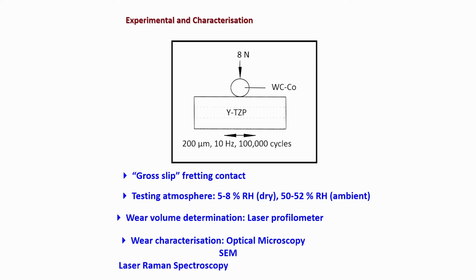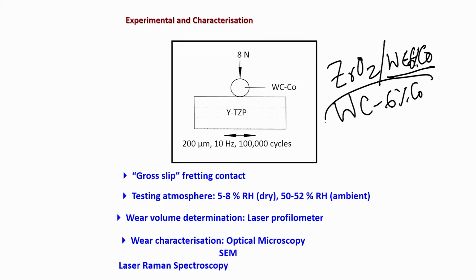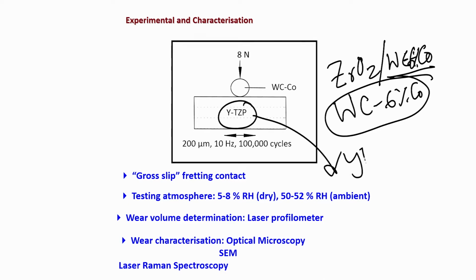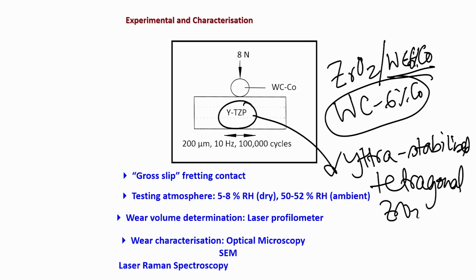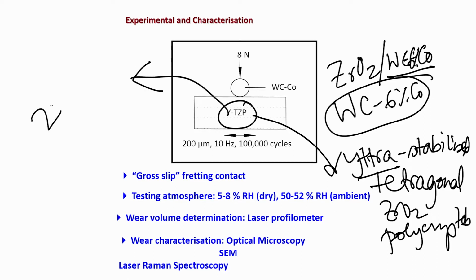So, we have not only used zirconia against transformation toughened zirconia in one of our studies. That is called self mating, zirconia versus zirconia. But in this particular case, we use zirconia versus tungsten carbide cobalt, which is a hard metal, and here the cobalt percentage is 6%. So, tungsten carbide 6% cobalt, that is a typical hard metal that we have used. Now, this Y-TZP stands for yttria stabilized tetragonal zirconia polycrystals. What it means is that you add yttria, so essentially this zirconia is yttria doped zirconia. The amount of yttria here is typically varied between 2 to 3 mole%.